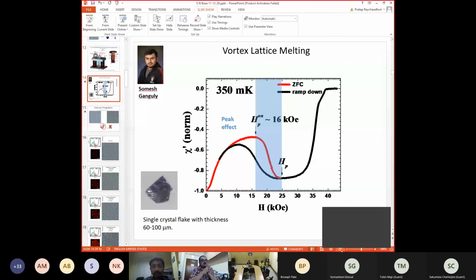Okay. And so have you tried to go down to thinner layers? Okay, so with niobium diselenide we did not, because the way we did it, we could not have gone much lower. What we do is we take a thin plate, as thin as you can judge by looking at it, and then we put scotch tape on it, and then in vacuum we pull it, so you expose the surface. Now, how much the scotch tape has taken along with it, we don't have control.